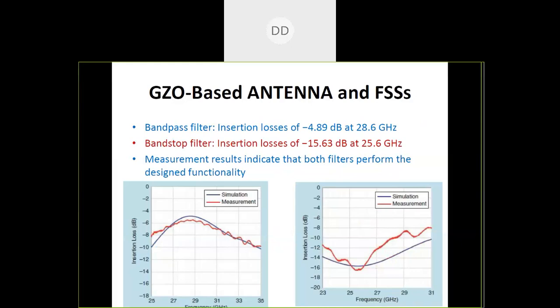frequency. Similarly, they analyzed the bandpass filter and bandstop filter performance using the experimental setup, and they found good agreement with the simulated and experimental results, which indicates that both filters perform the designed functionality. So here we can see that this is the resonance for the bandpass filter, and this is the resonance for the bandstop filter. So we can see that at the desired frequency, they had the desired minimum and maximum insertion losses as per the corresponding filter characteristics.